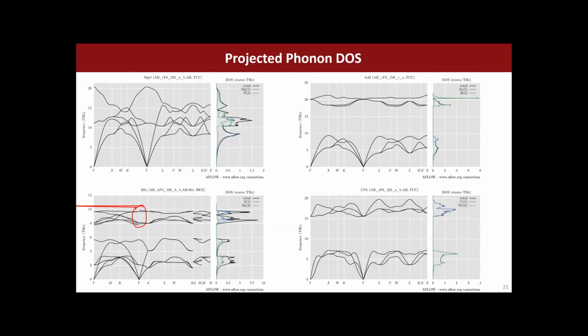But there are other methods where you have random or pseudo-random displacements, and you can do fitting of the potential energy where you include the LO-TO splitting. But that's more at the anharmonic calculation level, which is more expensive. But yeah, we cannot increase the supercell size because this correction or this effect is by definition not in the equation.